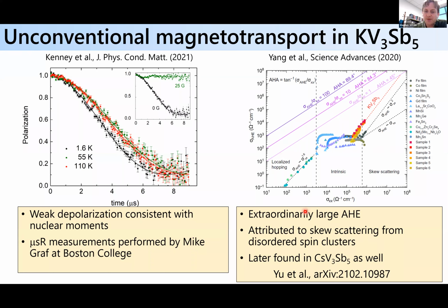So the initial mystery: this was originally attributed to potential skew scattering from disordered spin clusters, but in parallel, we were looking at this system with neutron scattering, and we saw really no signatures of magnetism. And we also gave some powders to our collaborator, Mike Graff at Boston College, and he did muon spin relaxation measurements and basically saw no signatures of electronic moments in the system. The entire relaxation profile he could model with just weak depolarization, consistent with depolarization arising from nuclear moments in the sample. So there's no real local moment electron magnetism that we can find in the system via μSR. So that's a bit of a mystery.